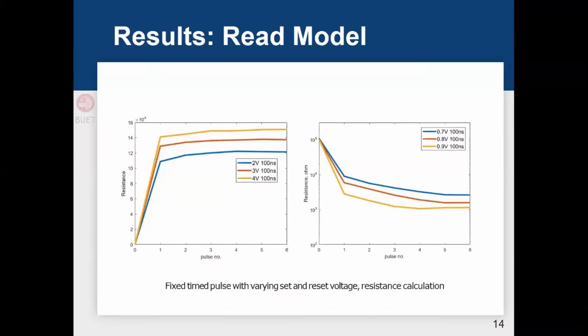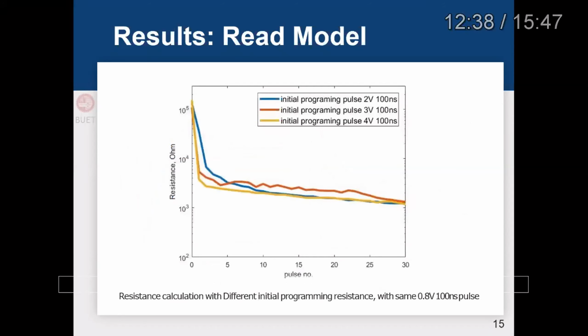And if we apply this same concept in the case of set operation, for example, if we apply a voltage value of 0.7 volt or 0.8 volt or 0.9 volt, as it's the set operation, the resistance should come down. It actually comes down, but depending on the voltage value or the pulse width, it actually settles down to a different resistance state. Initially, we implied this very thing, that phase change memory devices actually rely on this very property, that means the continuous transition between multiple stable states with the pulse width or the pulse voltage amplitude to get to the desired amount of resistance.